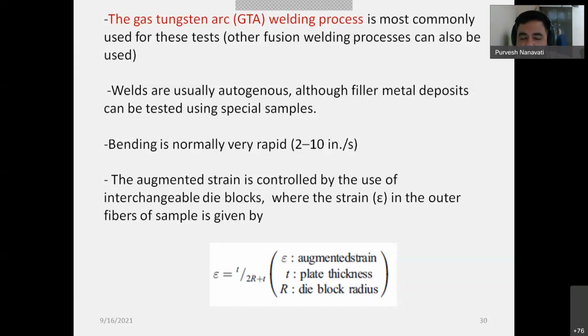Only the arc is generated, and the arc is directed on the test coupon and the test is conducted, right? But filler metal deposits can be tested using this special test. You know, there is a provision that if you want to find the compatible filler metal, you could perhaps first develop a molten weld pool, and you can dip your filler metal just like standard GTAW practice. You can carry out this test with the help of filler metal. So you can qualify filler metal for the particular test setup. And the bending is normally very rapid, right?